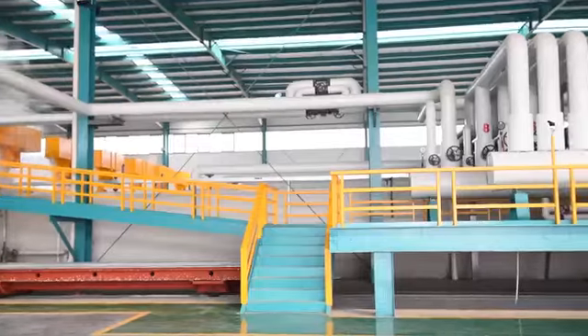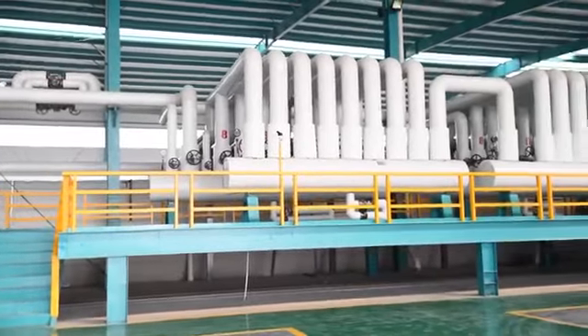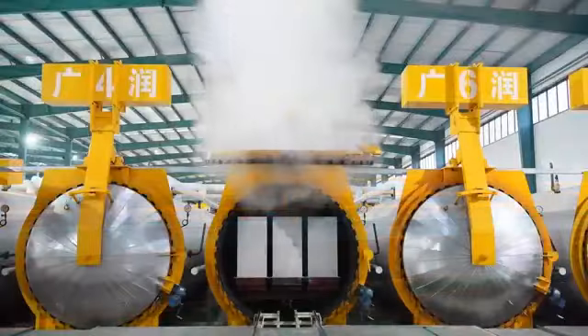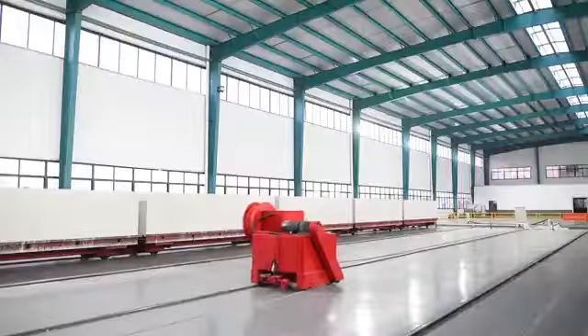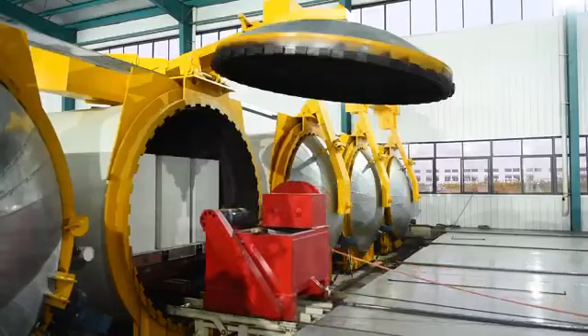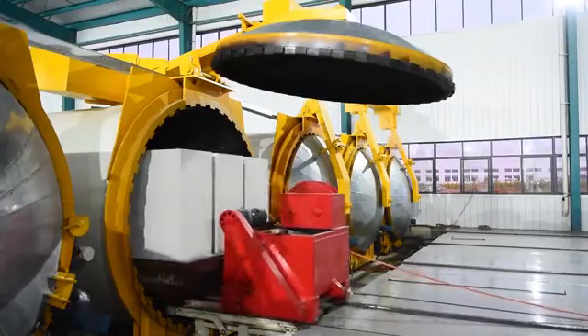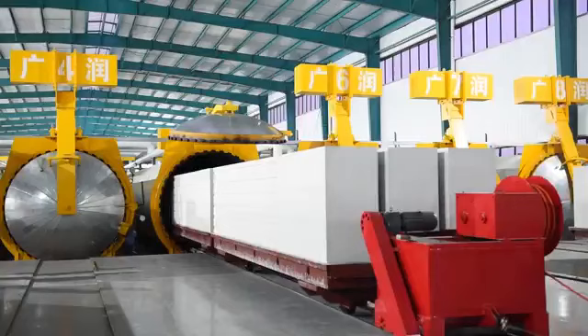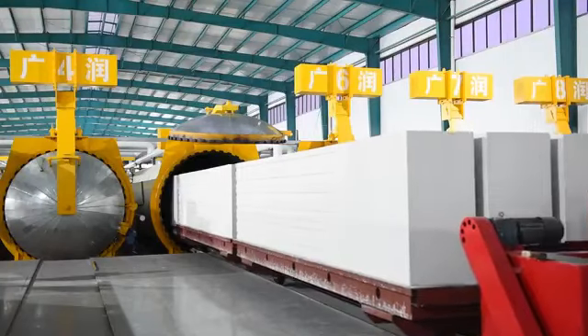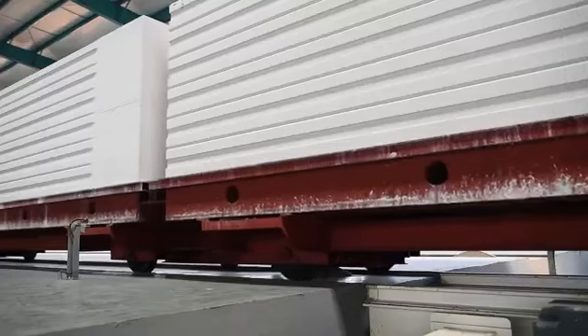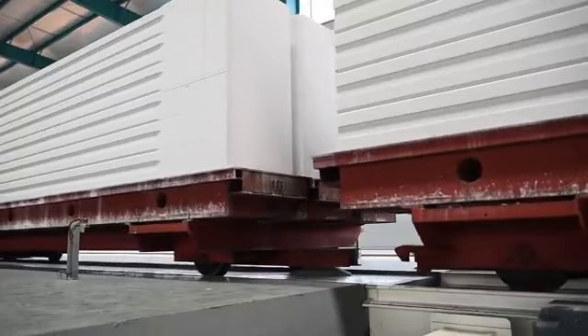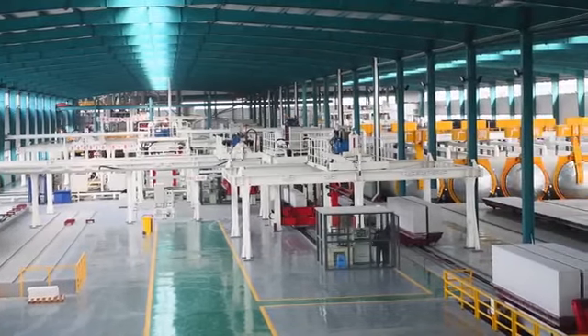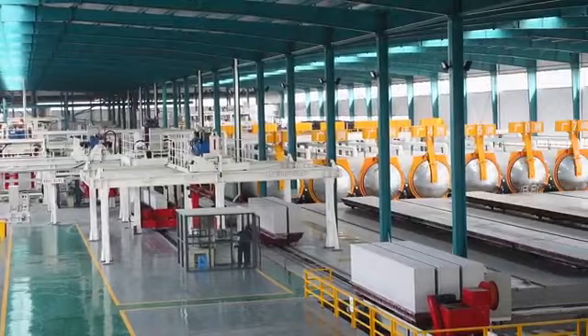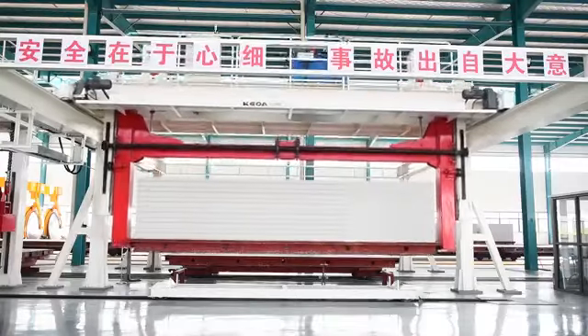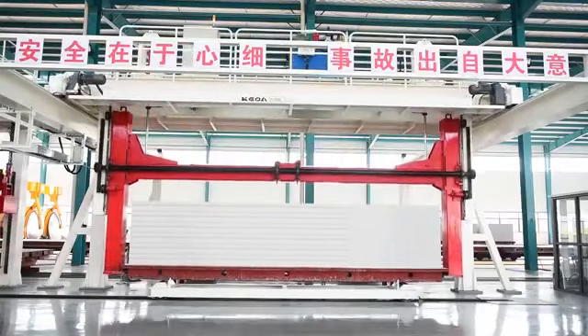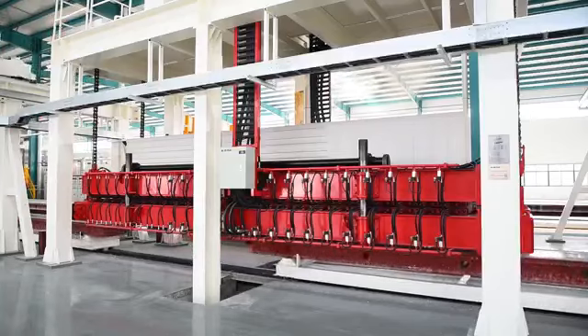After grouping, 3 molds curing cars will be pushed into the autoclave for curing 10 to 12 hours under 200 degrees Celsius, 1.2 megapascal. Steam and autoclave can be reused from each other to save energy consumption. The curing car with white cakes goes to the packing area, and then white cake will be separated by separator.